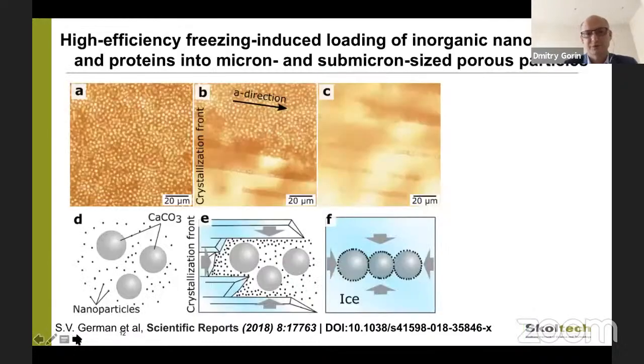And our postdoc from our group suggested using this freezing and thawing induced adsorption method. The idea: if we mix calcium carbonate particles and magnetite nanoparticles and then freeze this suspension, it's well known that ice crystals use water molecules for formation of the crystal, and the crystallization front pushes out magnetite nanoparticles and calcium carbonate particles, and as a result we obtained adsorption of magnetite nanoparticles on the surface of calcium